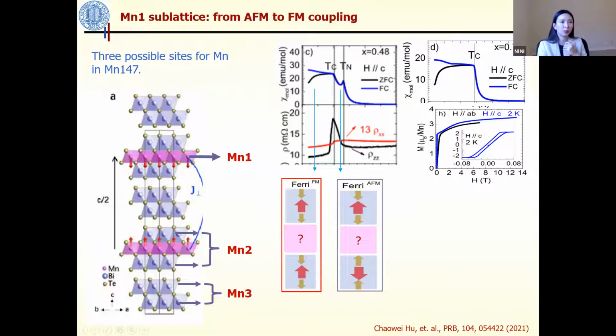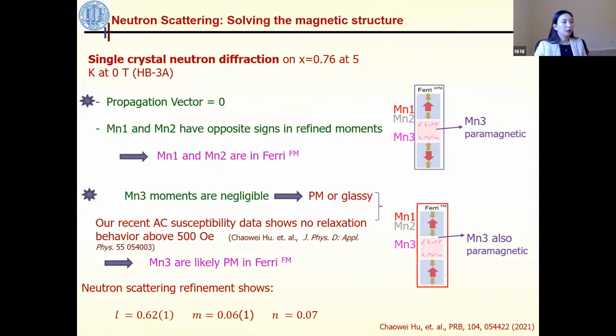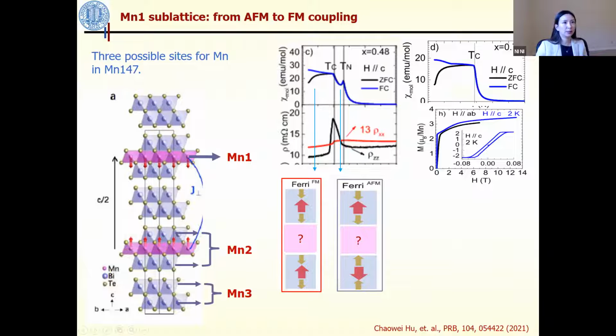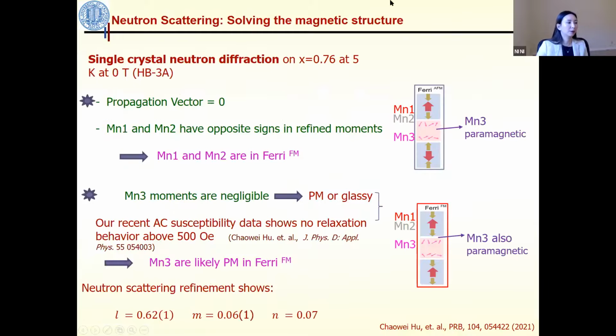But then the next question is, how does the manganese 3 order, right? How does the manganese 3 order? Okay, then we performed the single crystal neutron diffraction at the 76% doping level. It turns out that, indeed, based on our magnetic property measurements, the manganese 1 and the manganese 2 magnetic states from the neutron scattering measurement are consistent with our hypothesis.